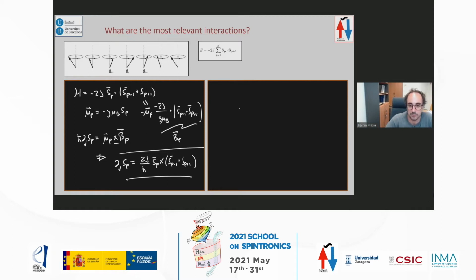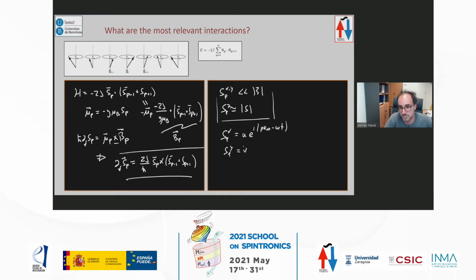So now we can try to solve this. The only thing for this exercise you have to take into account is that the components x and y of this vector are small, and the z component is basically fixed, more or less constant, with the value of S. So if we take this into account, and we say a solution of this type for x and the same for y, and we just change the amplitude, it's just like a cross.